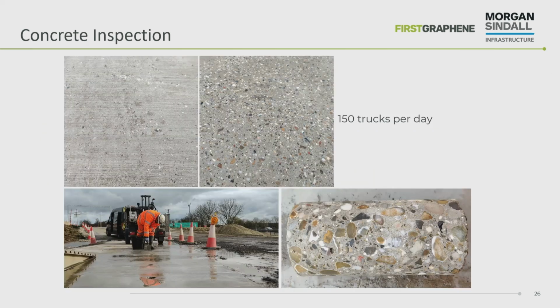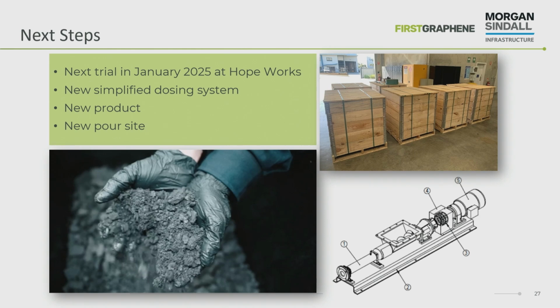The slab we got to visit a few months later. It was cored. You can see there 2 images of the surface, the unworn and the worn surface. It was 150 truck movements a day. This was over a wheel wash. This is a wheel wash slab. So a pretty brutal condition, a test scenario for this concrete. And yeah, so it performed adequately, just as you would expect. There was nothing unusual happening there. The cores looked fine. The surface looked as worn as you would expect. So yeah, there was nothing unusual there.